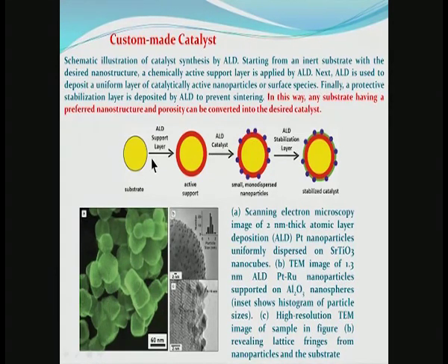And then, using ALD, you can see that there are speckles of platinum on top of these cubes. These transmission electron micrographs show clearly that there are tiny platinum particles, and therefore a very large surface area for them, given that they are so tiny, and excellent as catalysts.